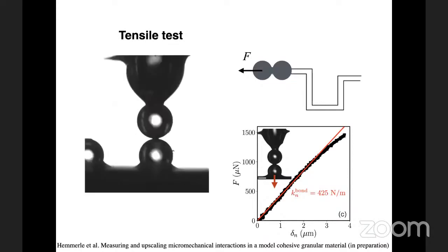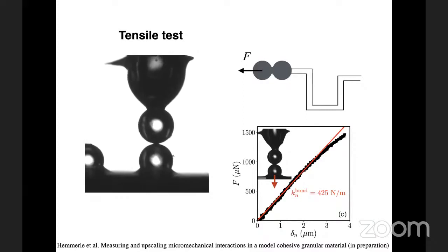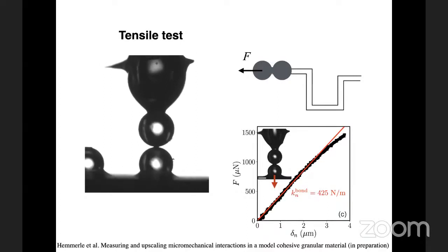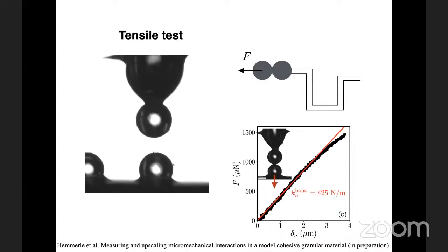So if we look at what happens there, we have the two beads and they will be pulling apart from each other. And I'll start the movie going. By measuring the displacement of the various objects in the image, we can measure a displacement between the beads by fitting circles to them. And we can also measure how much the micropipette has moved. We know its spring constant because we've calibrated against a hard surface. And so we can measure a spring constant of the bond.